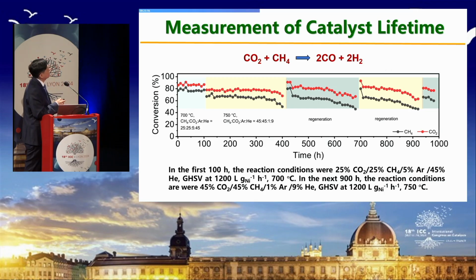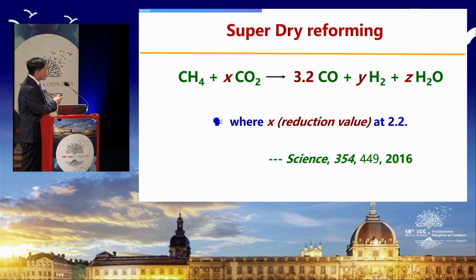Also for the catalyst life, even at 1,000 hours it is still very active, and even if it loses activity, after regeneration the activity returns back due to no change in the nickel nanoparticle size. Not only the dry reforming, even for the super dry reforming.